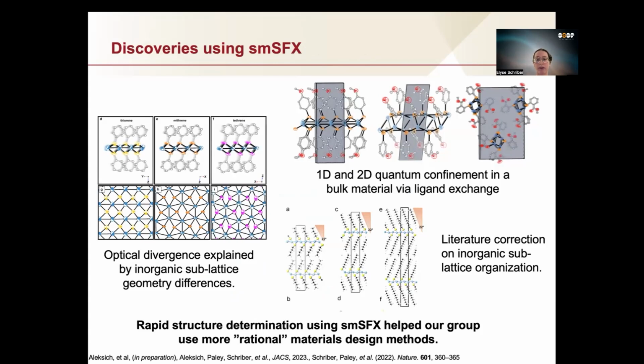So the small molecule SFX pipeline has been extremely successful for my graduate research group, and it has allowed us to explain optical divergence in 3 materials. We had no idea why 2 were photoactive and 1 wasn't, and it turns out that the inorganic sublattice geometry is very different than the one that's not photoactive, and you can actually see that here. We lose the argentophilic silver-silver bonding elements that give these two their photoactive properties. And that really answered a question that we hadn't been able to answer for 5 years.